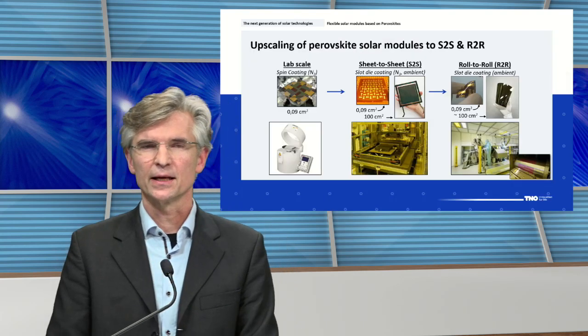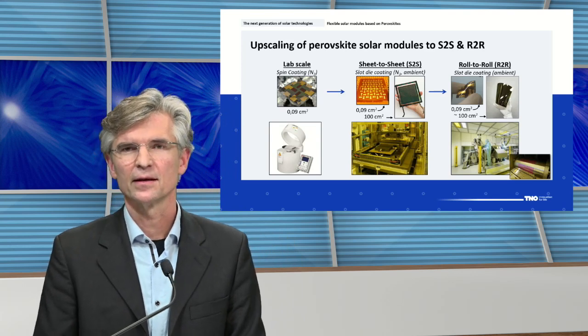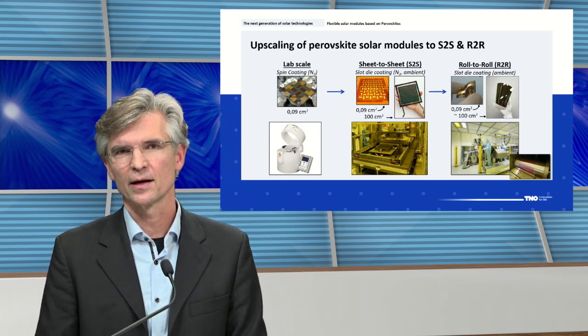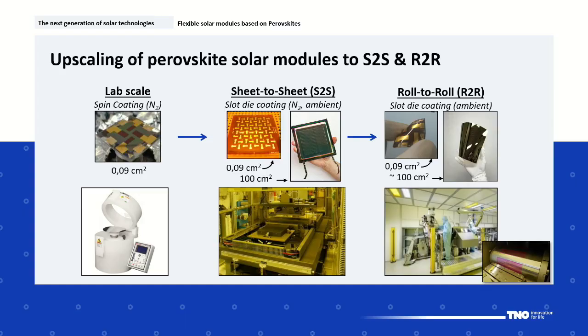So that is about scaling up the technology. And in this slide, you see how our approach is towards scaling from lab scale towards sheet-to-sheet and roll-to-roll. On lab scale, we make devices on substrate with an area of about 3 by 3 centimeter. And on this substrate, we have 4 devices. And the device active area is approximately 3 by 3 millimeter.